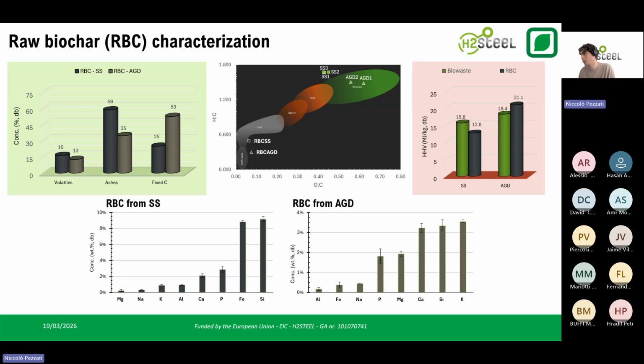And also during the thermal conversion, we see how the caloric density of the material changes. In particular, when treating the agricultural digestate, it is possible to increase the caloric density from the biowaste to the raw biochar, thanks to a lower amount of ashes and a higher carbon content, which becomes fixed carbon in the biochar.